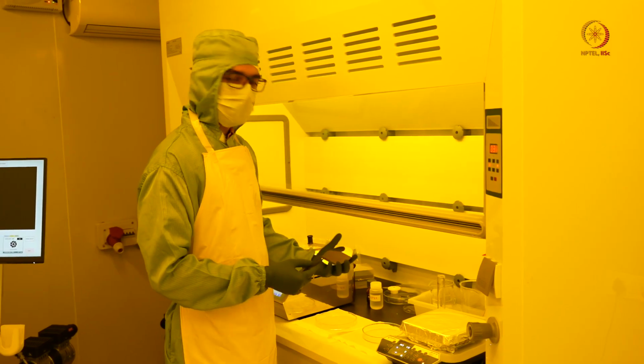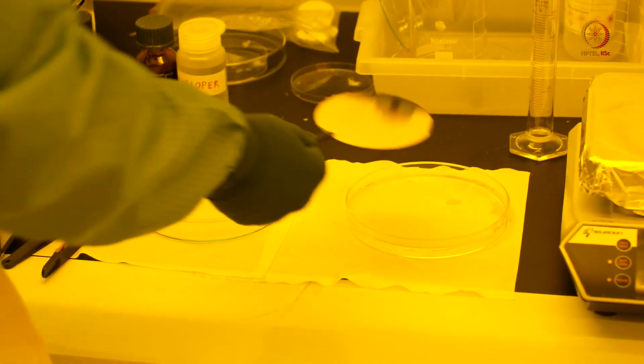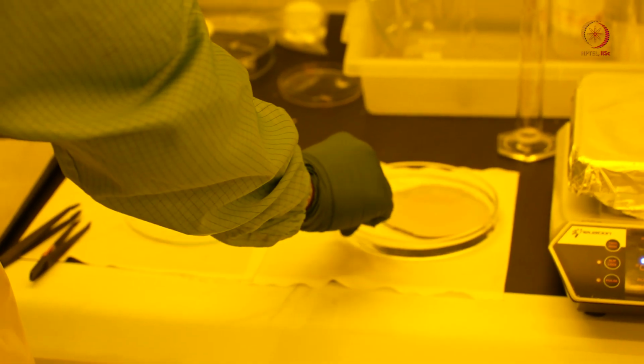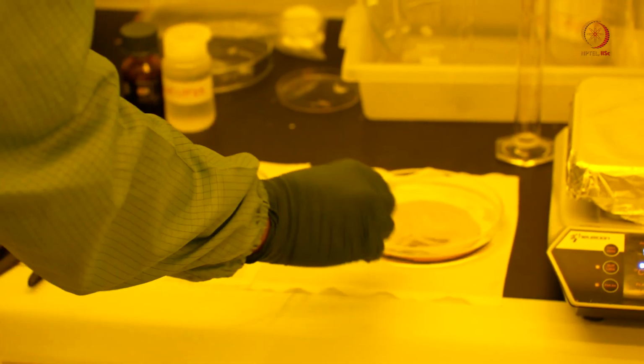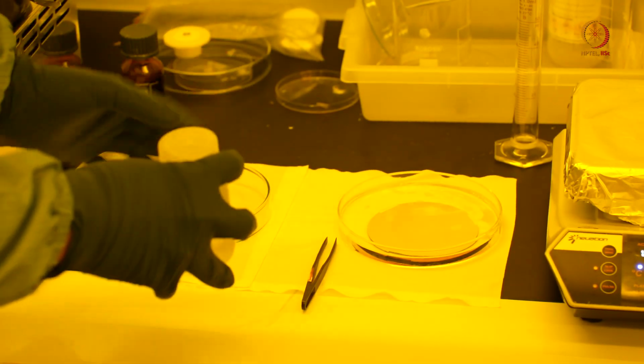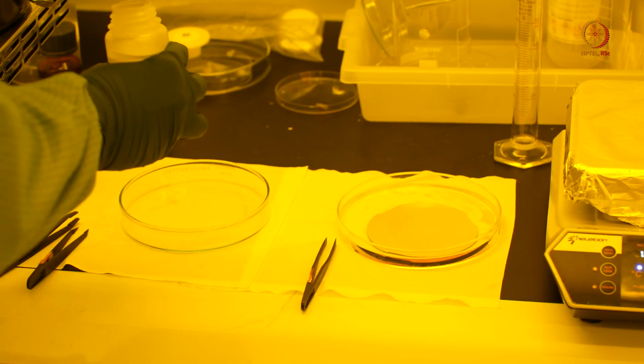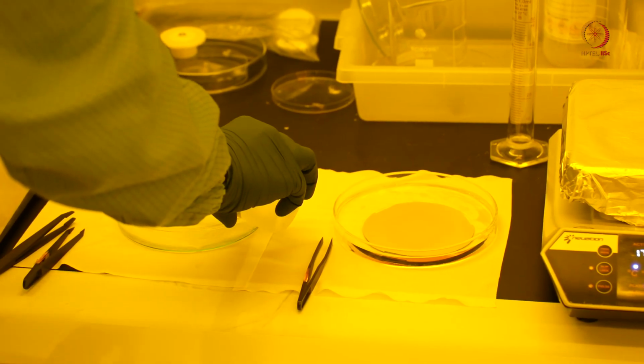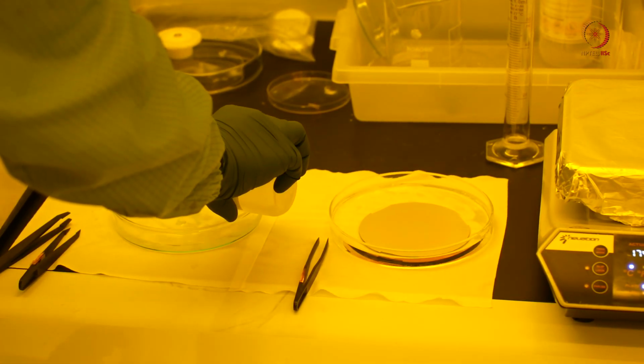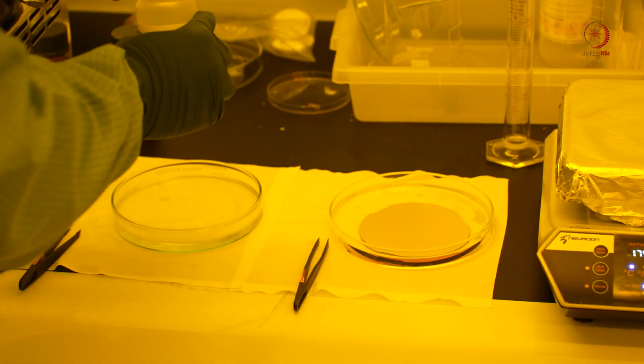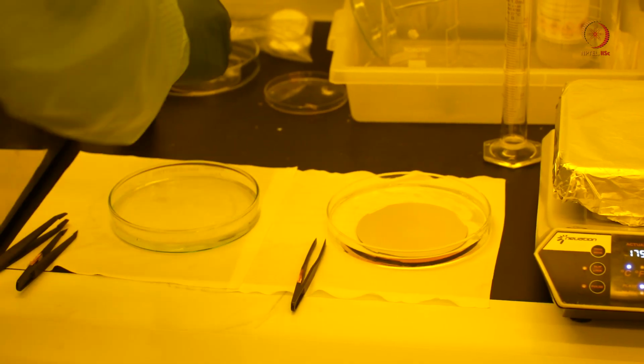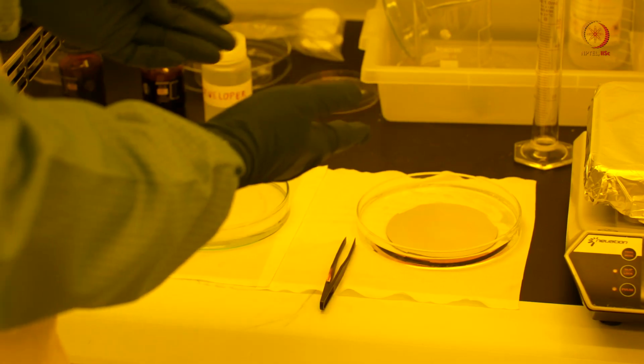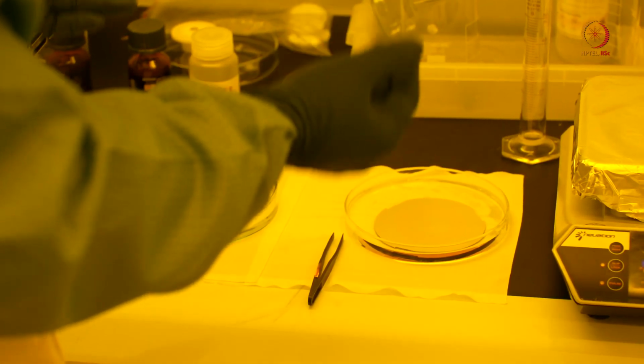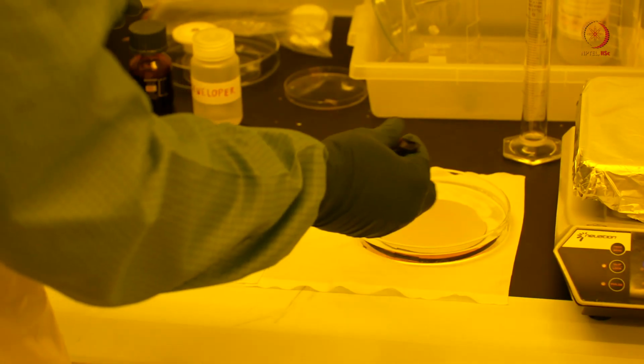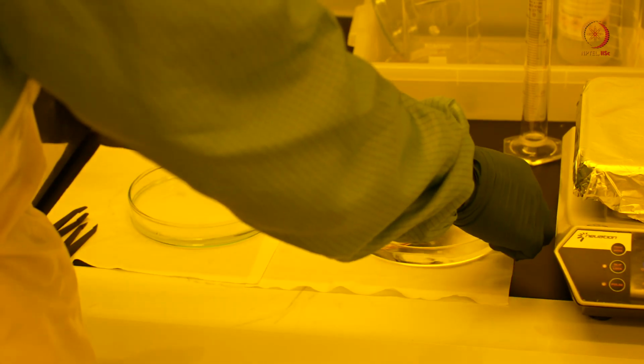We will do the development now. So I'm just placing the wafer in DI water for now, and I'm adding the developer solution. So the developer reacts with the photoresist and removes, since we are using a positive photoresist, it will remove the exposed area of the photoresist. And this typically takes around 20 seconds of time.